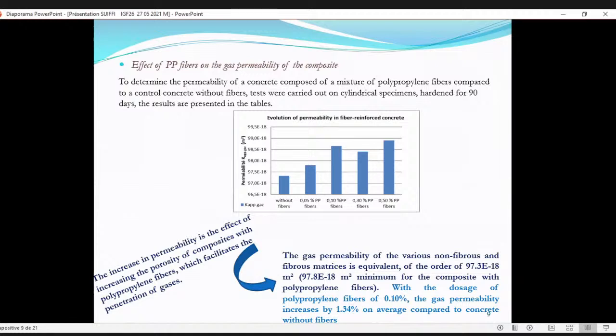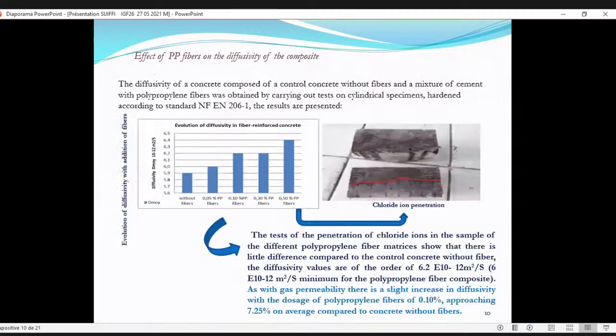For the effects of polypropylene fiber on the gas permeability of the composites, you can see in the figure that we have a slight increase of the permeability with the dosage of polypropylene fiber of 0.10%. The gas permeability increased by 1.34% on average compared to concrete without fiber. For the diffusivity of the composites, as with the gas permeability, there is a slight increase in diffusivity with the dosage of polypropylene fibers of 0.10%, approaching 7.25% on average compared to the concrete without fiber.